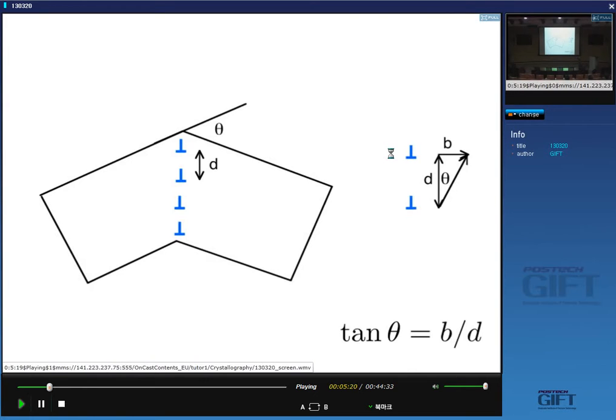by doing experiments in the electron microscope. So here is our boundary now, and the wedge that we had, the thin slice that we cut out to tilt the two crystals, is now filled with a set of dislocations. And the dislocations have a spacing, which is small d. And let's imagine always that we have a unit length into the plane of the board, so each one of these dislocation lines is 1 meter long into the board. And this is the tilt angle between the two crystals, which defines the orientation relationship, because that's a right-handed angle about an axis out of the plane of the board.